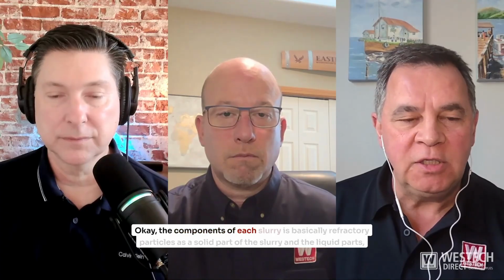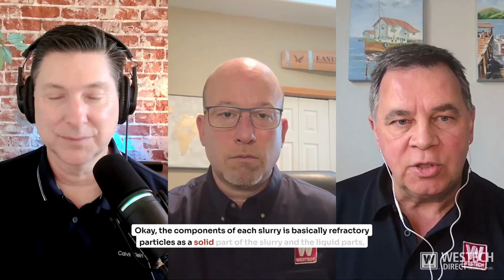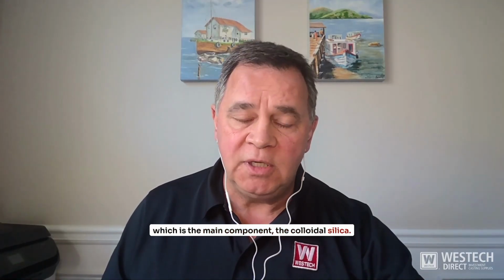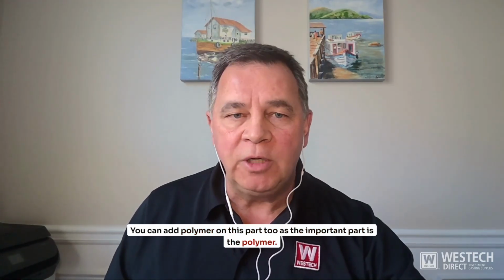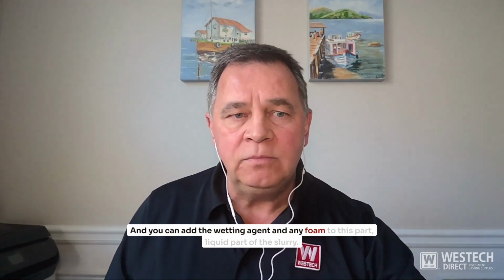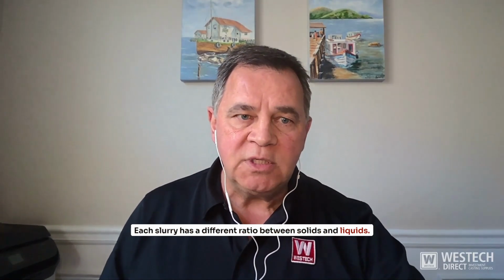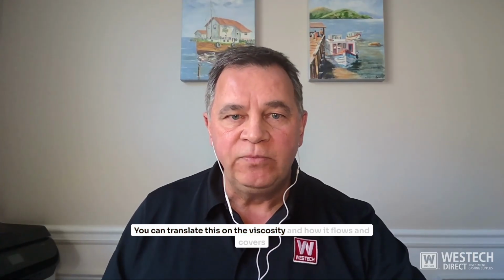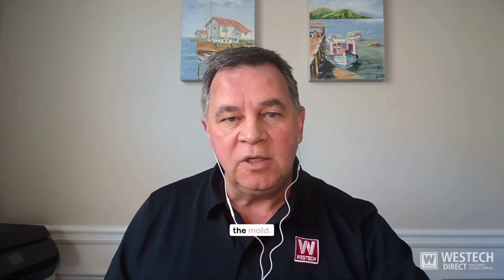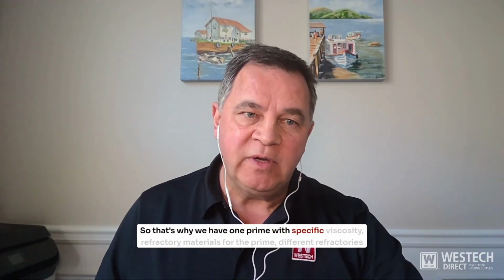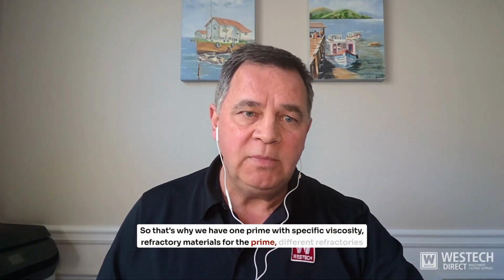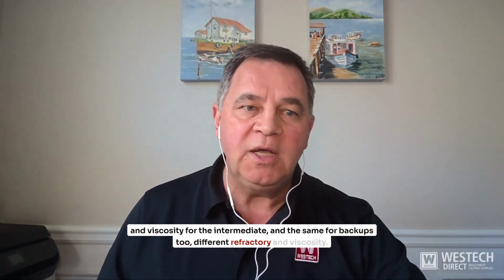Okay, the components of each slurry are basically refractory particles as the solid part of the slurry and the liquid part, which is the main component, the colloidal silica. You can add polymer to this part too, as an important part, and you can add wetting agent and antifoam to the liquid part of the slurry. Each slurry has a different ratio between solids and liquids. You can translate this into the viscosity and how it flows and covers the mold. So that's why we have a slurry with specific viscosity and refractory materials for the prime, different refractories and viscosity for the intermediate, and the same for backups too, different refractory and viscosity.